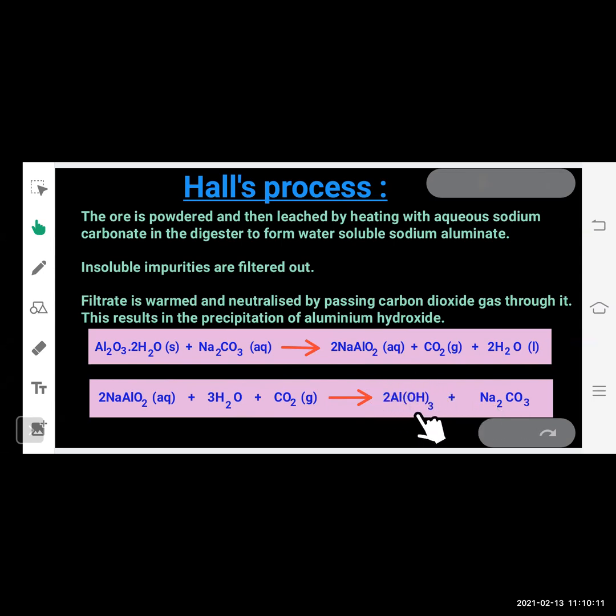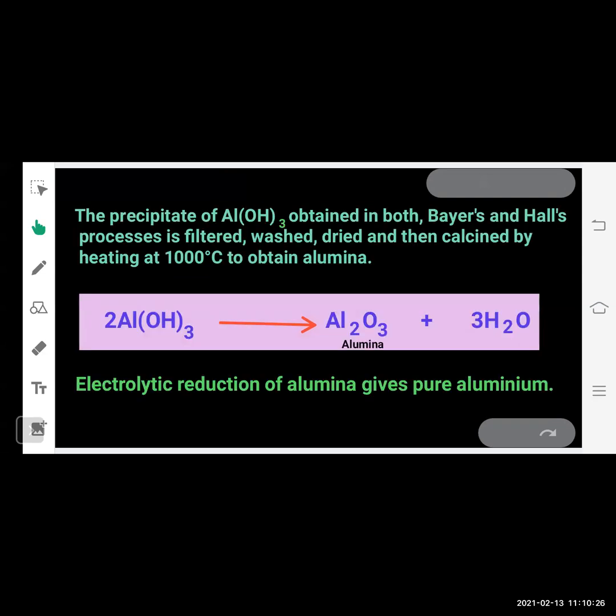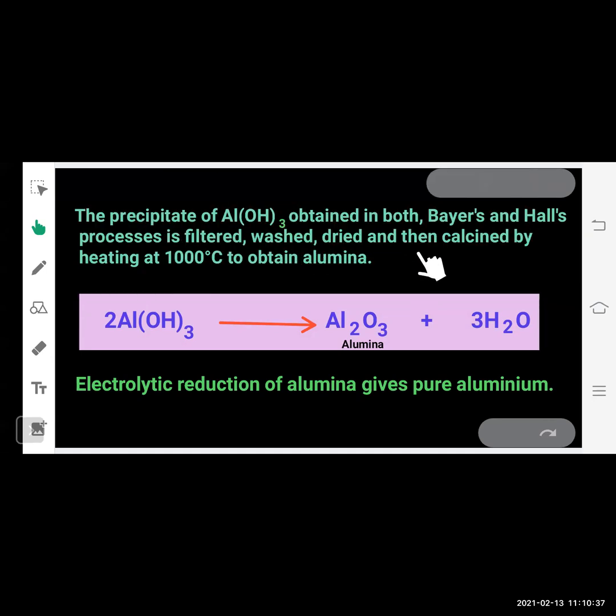As we can see, in the Hall's process and in the Bayer's process, we are getting finally aluminium hydroxide. So the aluminium hydroxide which is obtained from Bayer's process and Hall's process is again processed. The precipitate of aluminium hydroxide obtained in both Bayer's and Hall's process is filtered, washed, dried, and then calcined by heating at 1000 degrees Celsius to obtain alumina. So when it is heated at 1000 degrees Celsius, it gets converted into aluminium oxide, which is called alumina, and along with that, water is released. After that, the next process is electrolytic reduction of alumina. By the electrolytic reduction of alumina, we get pure aluminium.